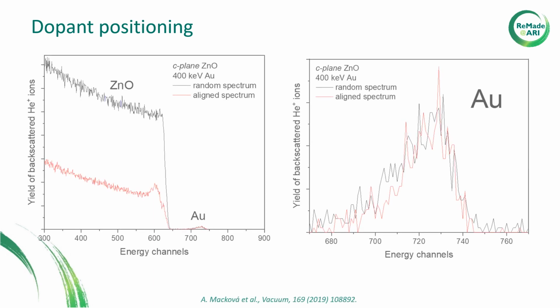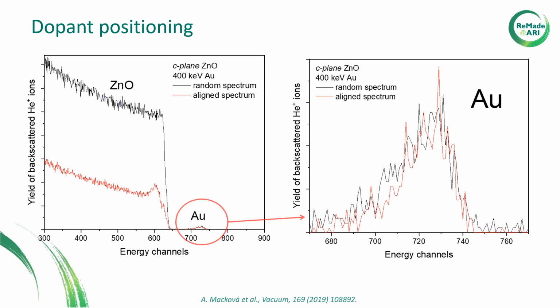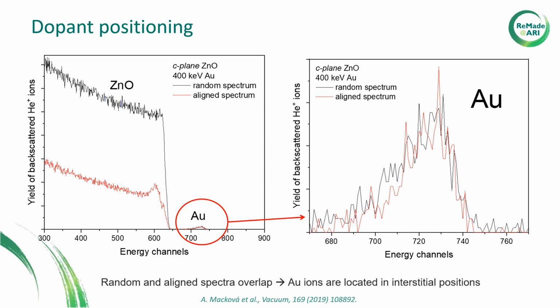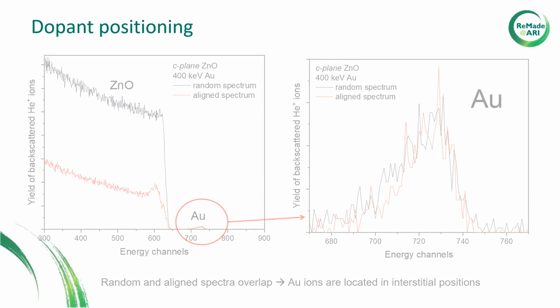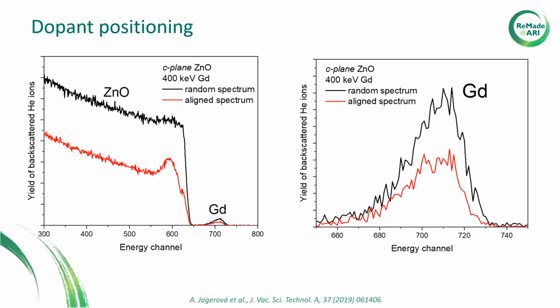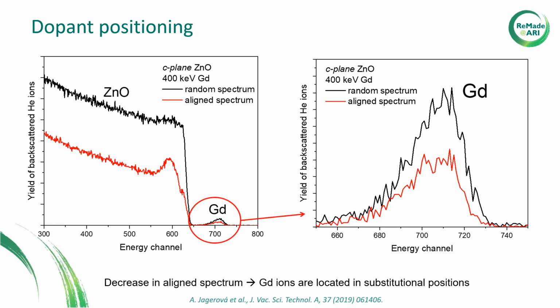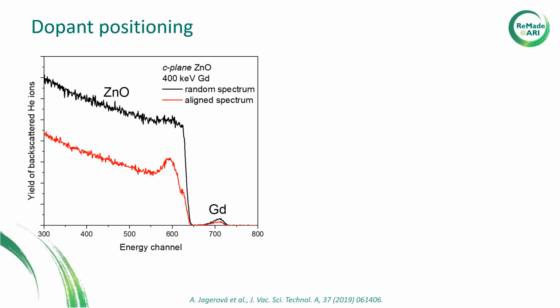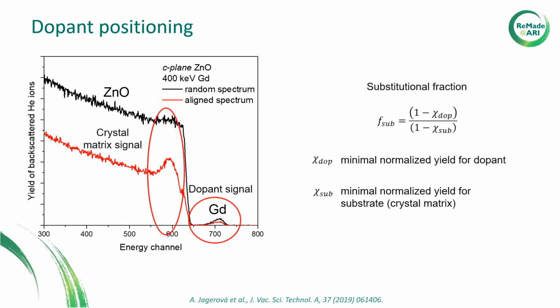The RBS in channeling mode can also offer information about preferential positioning of dopants or impurities in the crystal lattice. To get information about dopant position, we compare random and aligned spectra in the region corresponding to the dopant. If the dopant occupies an interstitial position, it blocks the lattice channel and both random and aligned spectra overlap. On the other hand, a dopant in a substitutional position allows free movement of probing ions, and we will observe a decrease of backscattering yield in the aligned spectrum. It is possible to quantify the percentage of dopant atoms in substitutional positions by calculation of the substitutional fraction.